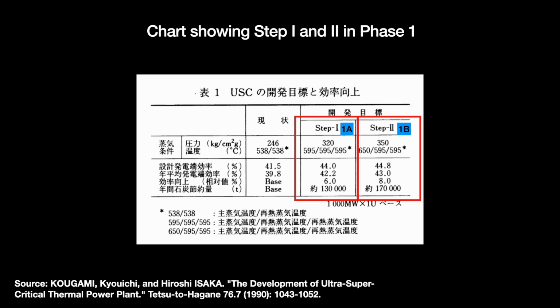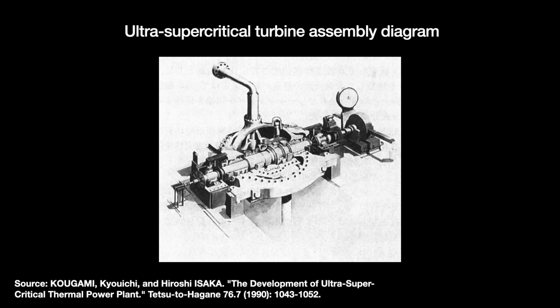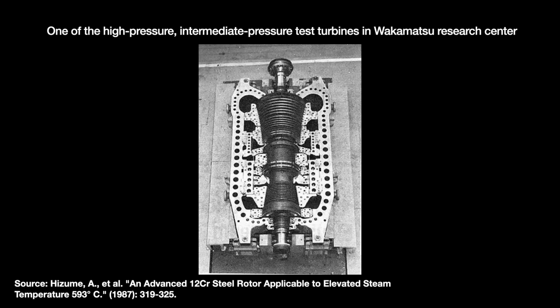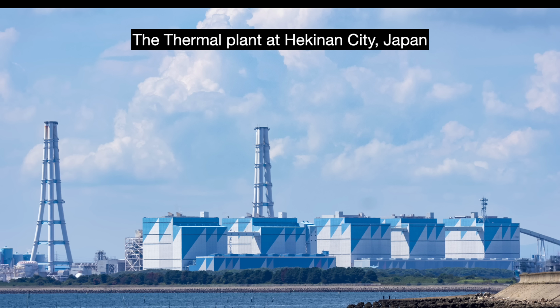There was great hope in this initially, but in the end the austenitic steels failed to work. Though blends were found that can sustain those temperatures, tests concluded that the thermal expansion coefficient still caused them to eventually warp and break. After building test turbines at Wakamatsu, Mitsubishi Heavy Industries leveraged the Phase 1A learnings to build the first commercial-scale ultra-supercritical turbine in the world, the 700-megawatt Hekinan Unit 3. Unit 3 operated at temperatures of 593 degrees Celsius. It first fired up in April 1993, marking a long-awaited return to ultra-supercritical conditions.